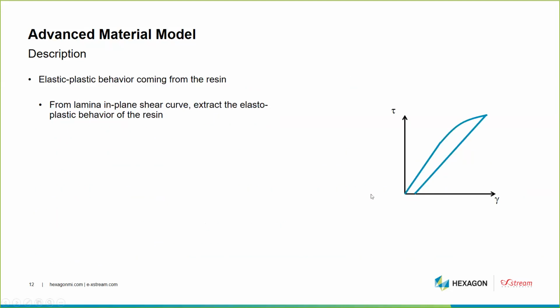So if we look into the detail of the key ingredients of this numerical model, the first point is that we use an elastoplastic behavior coming from the resin. And the way this elastoplastic behavior of the resin is identified, it's extracted from the in-plane shear curve of the lamina. So knowing the in-plane shear curves of the lamina, we are going to extract the elastoplastic behavior of the resin.